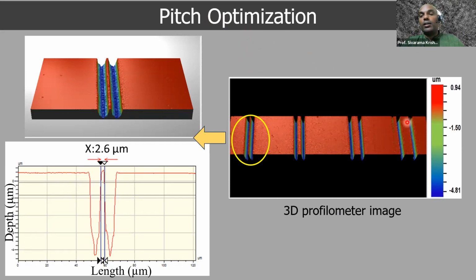You can see that a pair of grooves is written using this laser as a scribe. So there is a pair here, and these two grooves are coming close, and he wanted to try and optimize these grooves and bring them as close to each other as possible and determine a sort of pitch for these grooves. And he determined that we can space the two edges as close as about 2.5 microns together without destroying the integrity of the grooves and maintaining substantially good linearity among this.